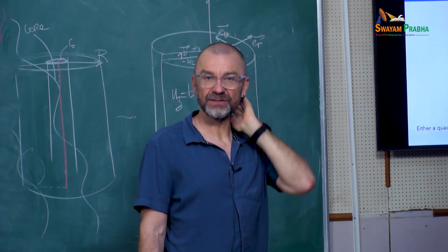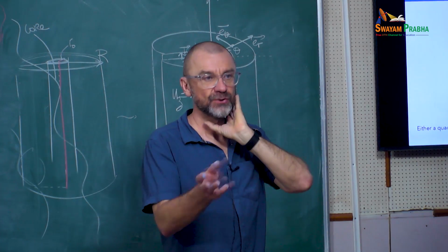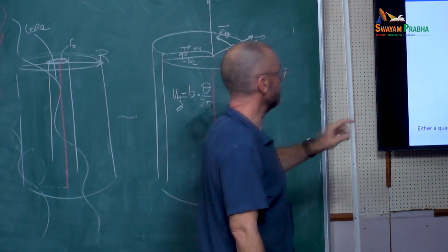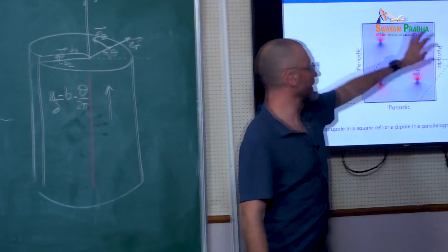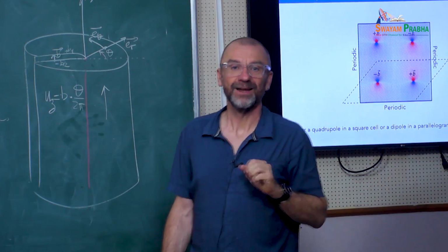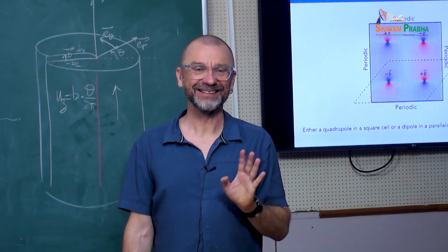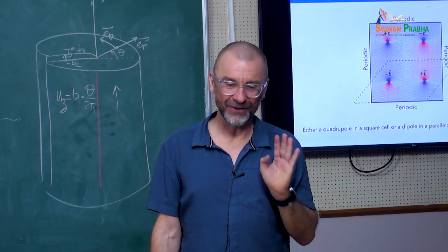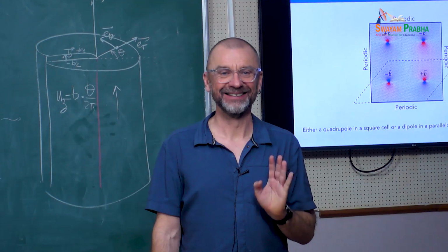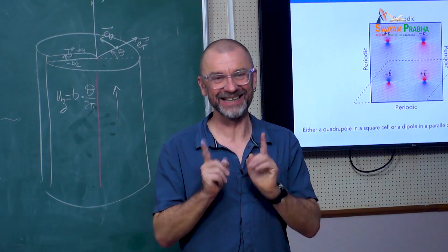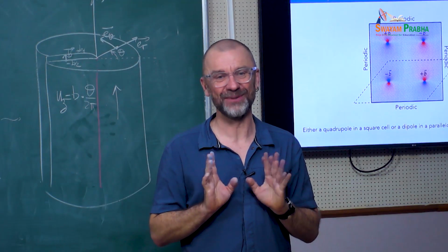You see the idea? So for those who will come to my talk this afternoon, when we do DFT, this is the cell that we use because we don't want to have the free surfaces. In DFT, several of our PhD students lived with 135 atoms. The cell is 135 atoms, and we put 2 dislocations in that crazy small cell.